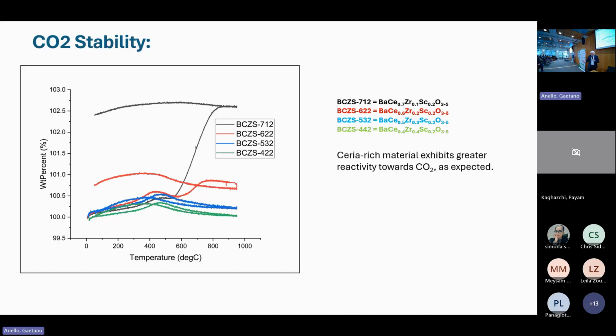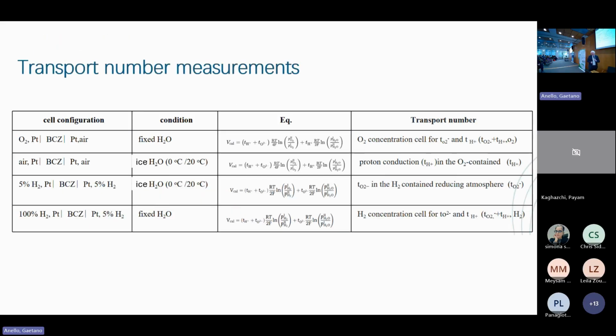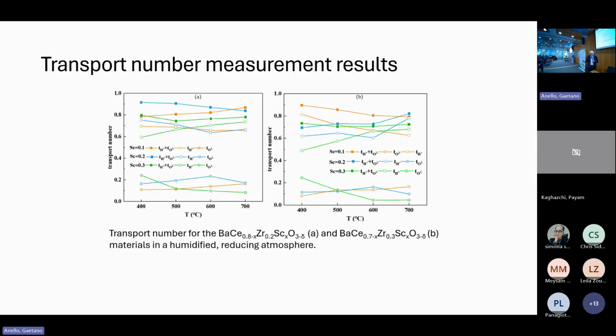How do you measure transport number? There's a lot of things happening. There's oxygen ions moving, there's holes moving, there's protons moving, and you have to look at very different scenarios. So you have to control the electrodes, controlling the water content, the oxygen content, and the hydrogen content. And by doing that, you can extract mixed conduction under oxidizing and reducing conditions.